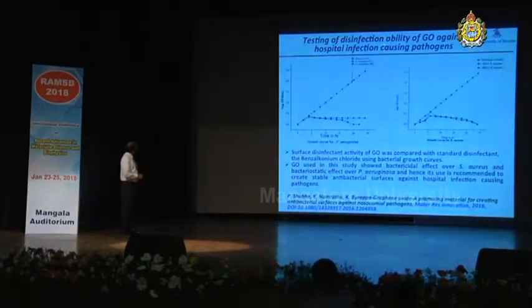And also we have tested the graphene oxide against hospital infection causing pathogens, and we have obtained some very exciting, encouraging results. We are going further into deeper studies. Graphene oxide used in this study showed bactericidal effect over S. aureus, and bacteriostatic effect over P. aeruginosa, and hence its use is recommended to create stable antibacterial surfaces against hospital infection causing pathogens, and we are further working on this.